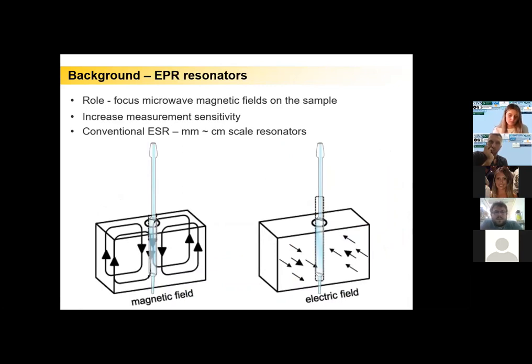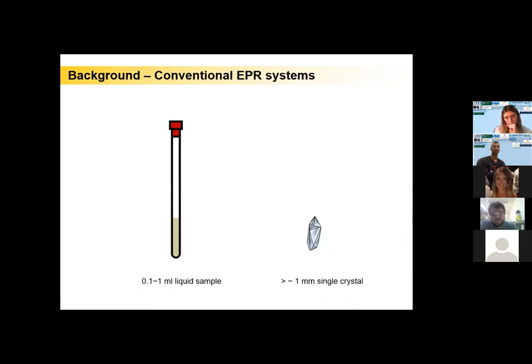Okay, so the EPR resonator is the heart of the system. Actually, it's a small box that is around 1 millimeter to 1 centimeter. The role of this box is to focus the microwave magnetic fields on the sample, and this is how we increase the measurement sensitivity. So what samples can we usually measure? Liquids, around 1 milliliter. And if we want to measure single crystals, they have to be bigger than 1 millimeter. So if we want to study samples that are smaller, like microcrystals or sub-nanoliter liquid samples, what we need to do is increase the sensitivity.